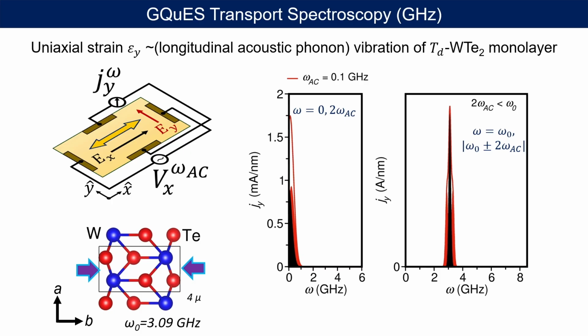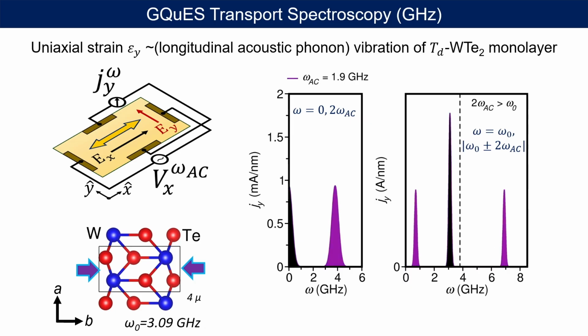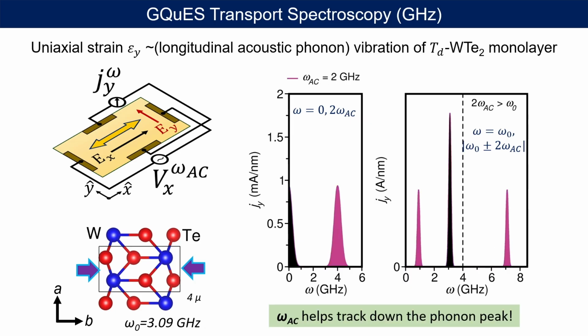You have a channel, you apply electric field with a frequency omega AC, and measure Hall signal as a function of frequency. And the prediction clearly shows that, in fact, there will be 2 side peaks associated with this applied frequency, and using them, you can easily tell what the vibrational frequency is. Yeah? So this is a specific prediction I think should be observable.